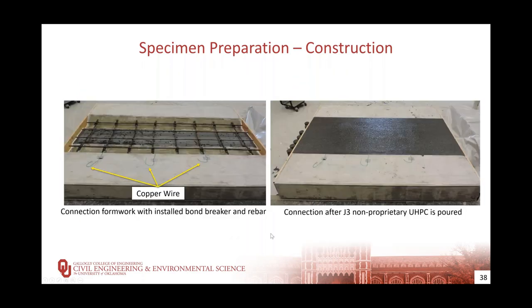After the bond breaker was placed, the exposed rebar was spliced together with more number 5 rebar, with number 4 bars tied in along the width of the connection, all in accordance with the New York State DOT detail. 3 of the splicing pieces had copper wire soldered to them to prepare for corrosion testing, as seen in the left photo. Once all the rebar was tied in, the copper wire was taped down for the pour to prevent the wire from being covered in the pour or being pulled out. The picture on the right shows one of the J3 mix connections just after it was poured.